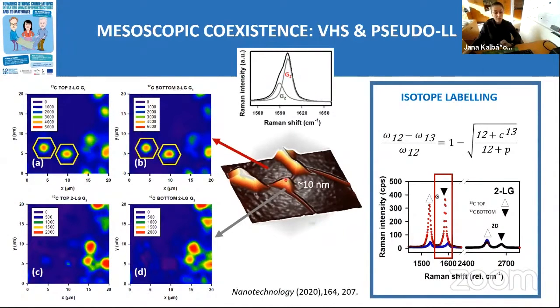Nevertheless, I forgot to mention the other feature which we have in this sample, and those are these corrugated areas. Of course, we cannot really easily see them on these, let's say, dominant G-mode maps. Nevertheless, if we inspect in more detail the fine structure of the Raman mode, we can easily recognize some kind of extra band which appears here.